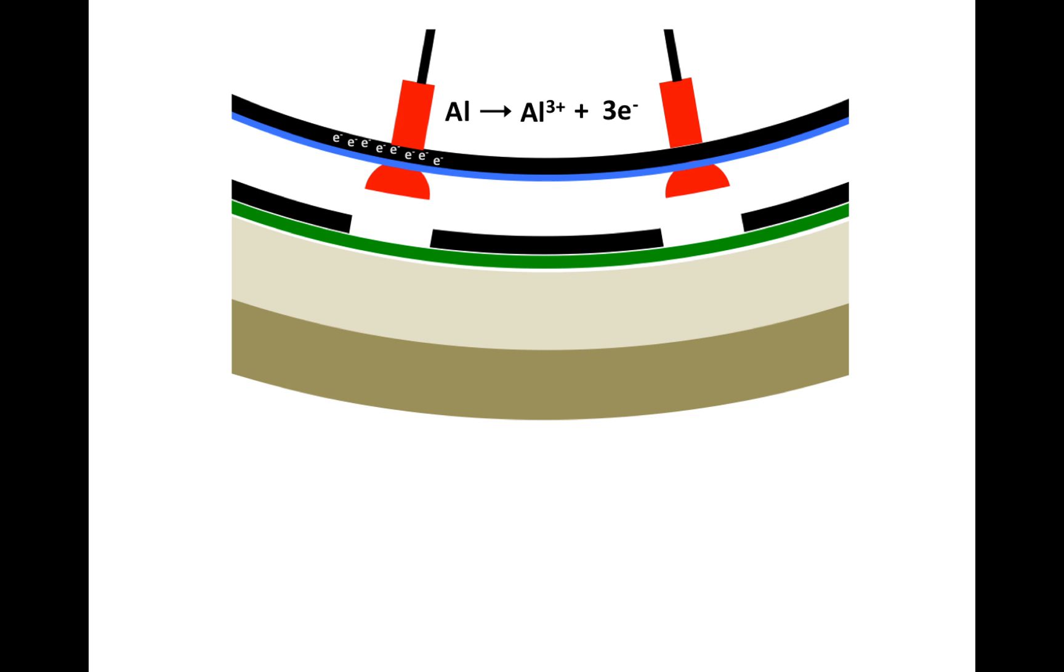And this has very severe implications, because the importance of this geometry is significant. A very large cathode area, which we have connected to a very small anode area, which we have, is the most unfavorable ratio in most practical corrosion situations.